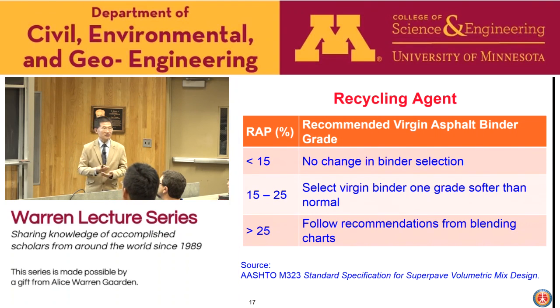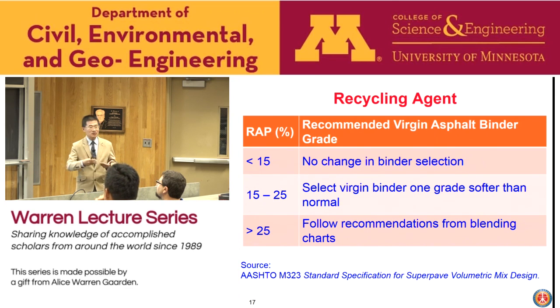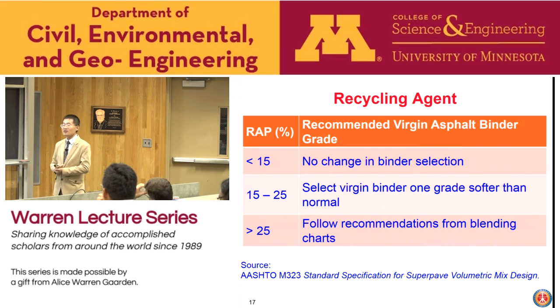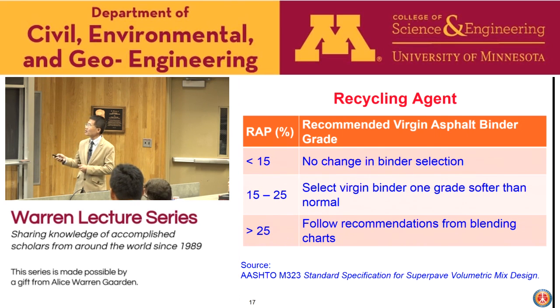Guidelines for the use of the asphalt recycling agent can be found in the asphalt specifications. When the RAP content is less than 15%, the contribution of the RAP is too small to make any difference, so there's no change in binder selection. When the RAP content is between 15 and 25%, the new binder should be a softening agent, as I mentioned previously, and it should be dropped one grade lower than the normal one. So in this case, we use AC10, which is pretty much equivalent to PG 58-22 here in the US.